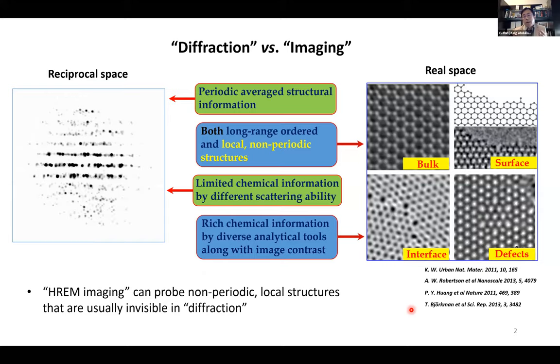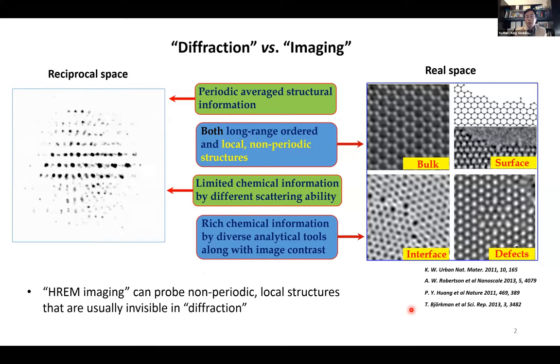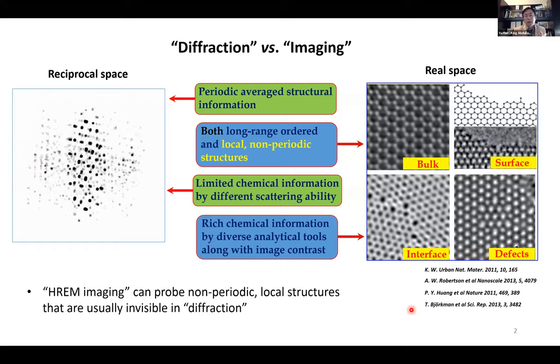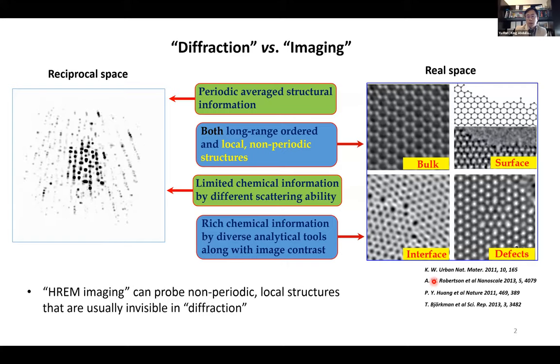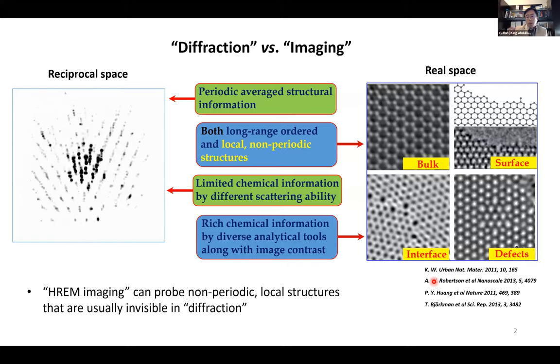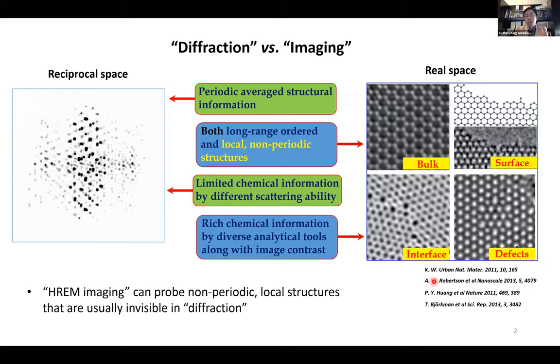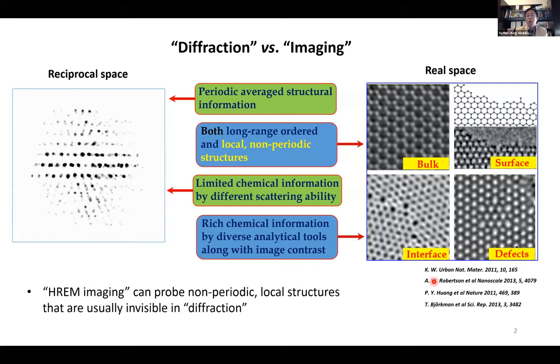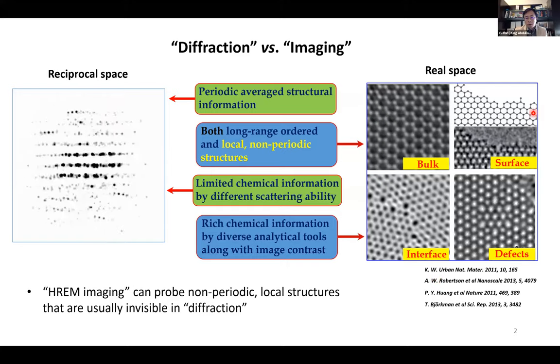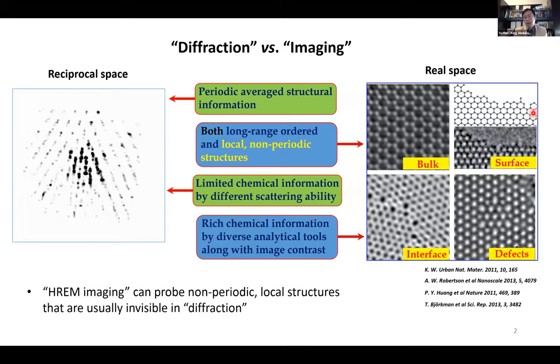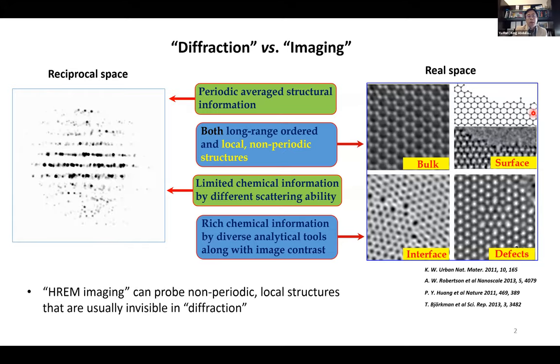The outcome of diffraction is a unit cell, which represents the average bulk periodic structure of the crystal. We can also study the crystal structure in real space by using high-resolution imaging techniques, for example using HRTEM. The advantage of imaging is that it can study both the bulk periodic structure and the local non-periodic structures, such as crystal surfaces, boundaries between crystals, defects, and gas molecules. These local features are non-periodic, so usually they are not visible in diffraction.